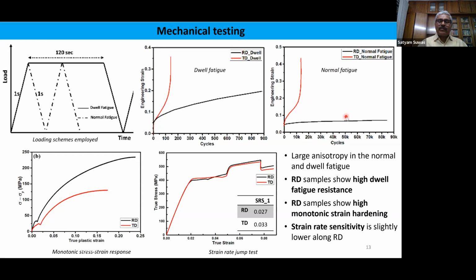We did some normal tensile tests, and we monitored the mechanical properties along both the directions, and this was the response. So the TD material has shown a lower strength and ductility, when compared with the yield strength of the material. We also calculated the strain rate sensitivity, and we have seen that the strain rate sensitivity values were slightly different in both cases, and only slightly. It was lower along the rolling direction, and the rolling direction sample has shown high dwell fatigue resistance, while it also showed high monotonic strain hardening. So this was the one which we saw.